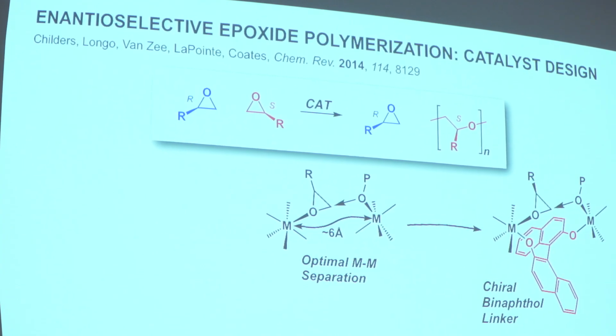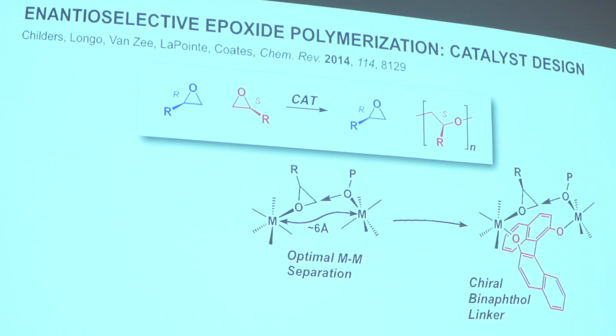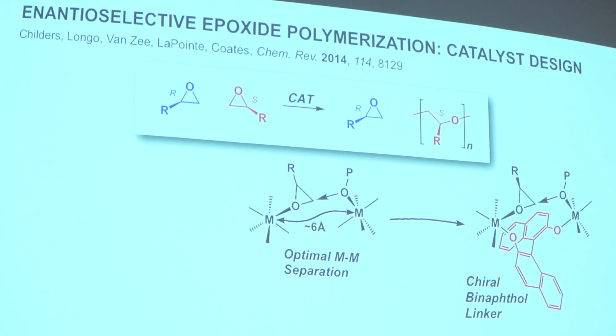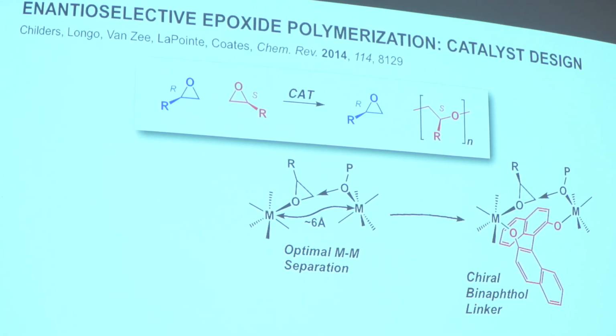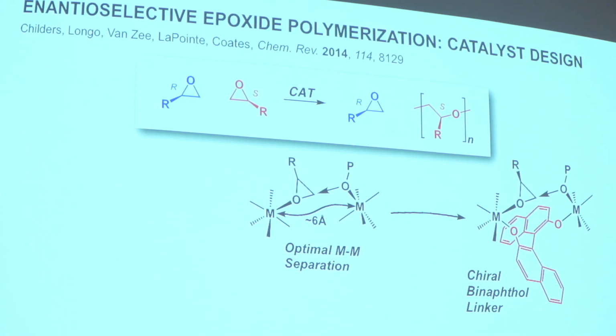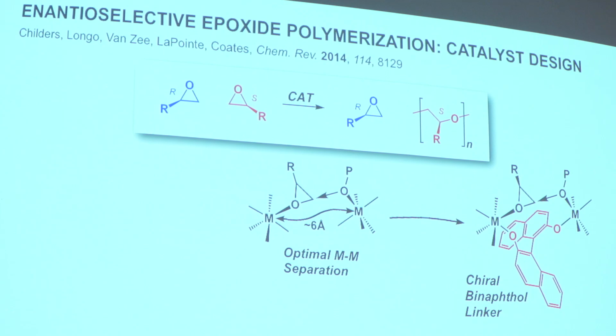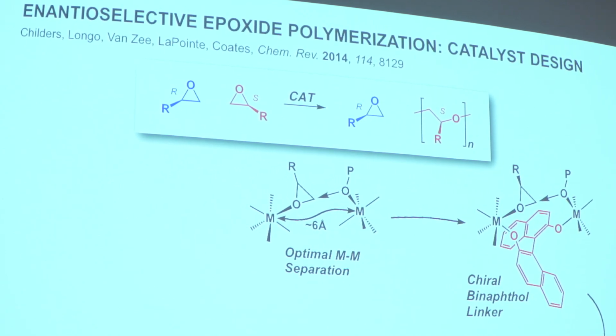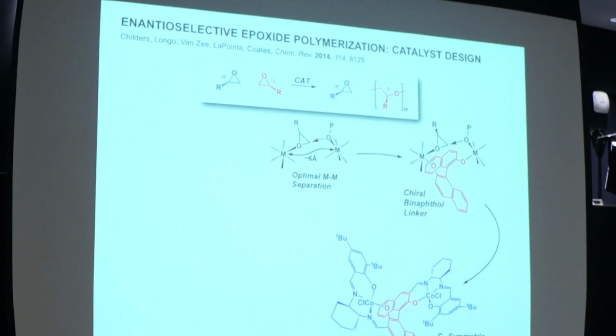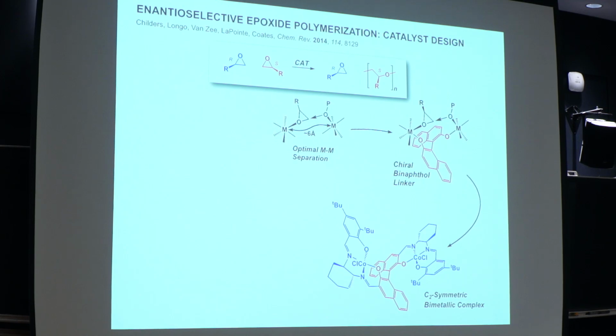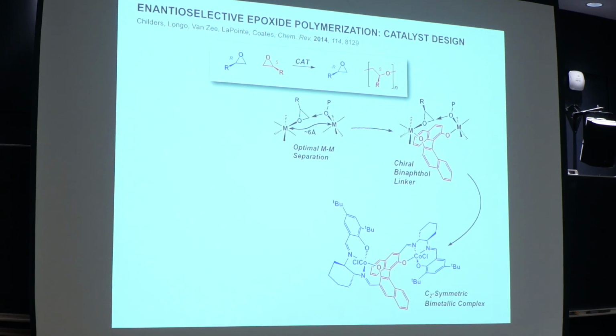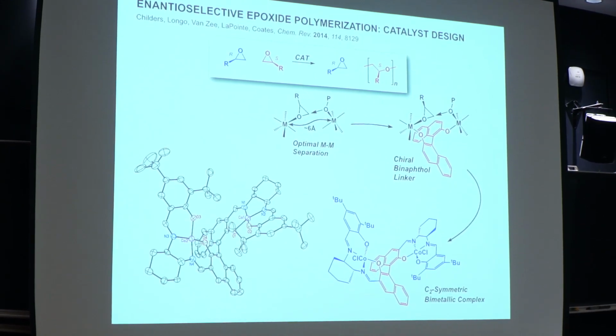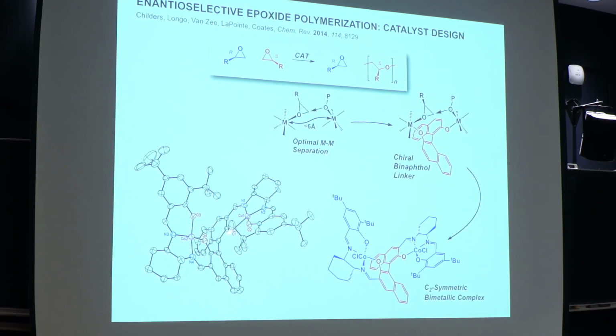We needed to add an element of chirality, but also give these metals a little flexibility so that to bring in the epoxide, you might have to open up the cleft. During attack, if you have a really rigid catalyst and you haven't designed it quite right, your activation barrier is going to be really high. This binol is good because it has some molecular flexibility between these two binol units. So we now need to pick some metals and carve out the ligand site around the different metals. We opted to go with some cobalt salens, given our experience in making the epoxide CO2 polymers. I should point out that this half is what the beautiful catalyst that Eric Jacobsen developed for the hydrolytic kinetic resolutions. So we developed some of these catalysts. If you're an inorganic chemist, we can show that we've made these by crystallography. You can actually measure the cobalt-cobalt separation. This is the C2 form.